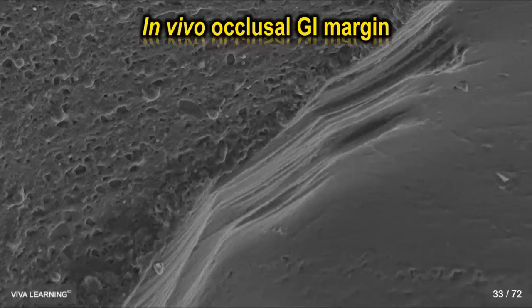But if that tooth had actually demineralized, the burr cut marks would be obliterated, and we would actually see this really porous enamel structure developing. But you don't see that with glass ionomer because that margin is so strong, it's going to remain the strongest part of the tooth. In fact, if we analyze the ion content of where those burr marks are, we probably would find that there's different ionic concentration of the enamel where those burr cut marks are than there is out on the other surface of the tooth where there never was glass ionomer, because those ions diffuse between the glass ionomer and the tooth.